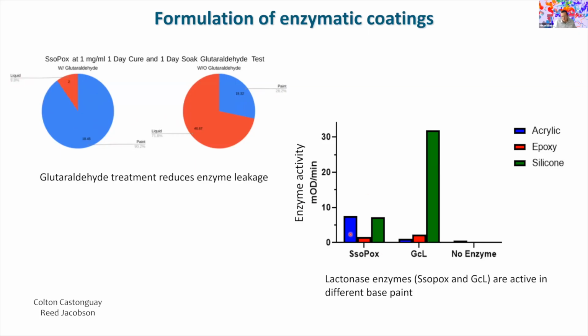And we also verified that these enzymes can be compatible with a variety of different coating bases, not just silica coating base, but more commercially available coating bases such as acrylic, epoxy, and silicone. And while the activity of the enzyme varies very strongly between the different coatings, you see that, for example, the activity in silicone base is very high for this enzyme compared to the activity in acrylic. There is activity in all of these different coatings that can be detected.